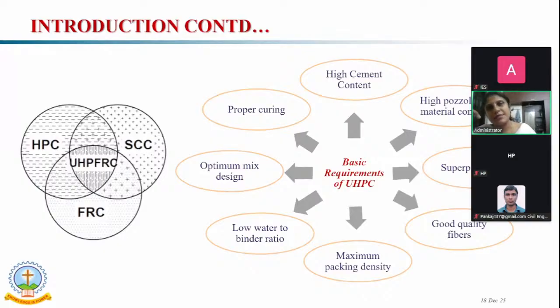The main criteria we are considering for ultra high performance concrete are a compressive strength beyond 120 MPa and a flowability of minimum 200 mm. Since, as I said earlier, it's just like a self-compacting concrete. In order to get the flowability of 200 mm with the low water to binder ratio of 0.17 and 0.18, it is very difficult to achieve. So we have to consider high-end superplasticizers. We have considered PCE-based superplasticizers.